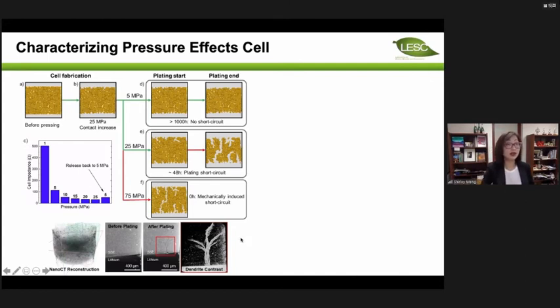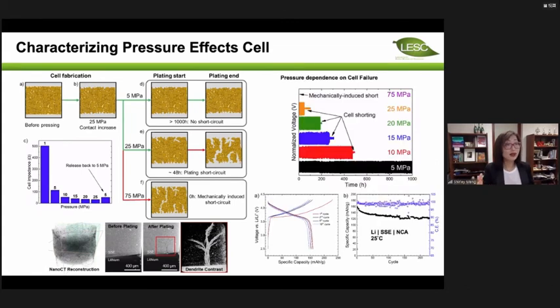When we found that, to our surprise, the lithium metal anode only cycles when you release the pressure to 5 megapascal. But if you have completely pressure-free, if you don't add any pressure, you also cannot cycle the cell. So we are only at the very beginning of lithium metal based solid state batteries, because even though, in publication, I can show you this is quite stable cycling.